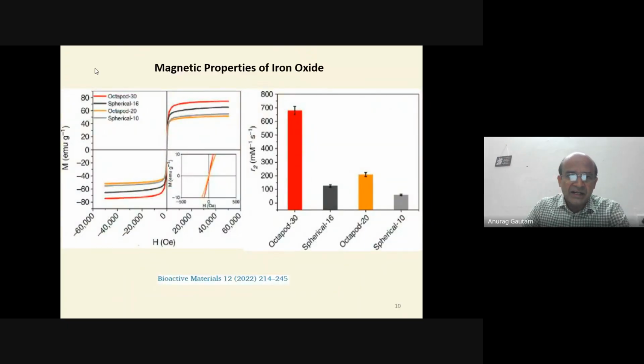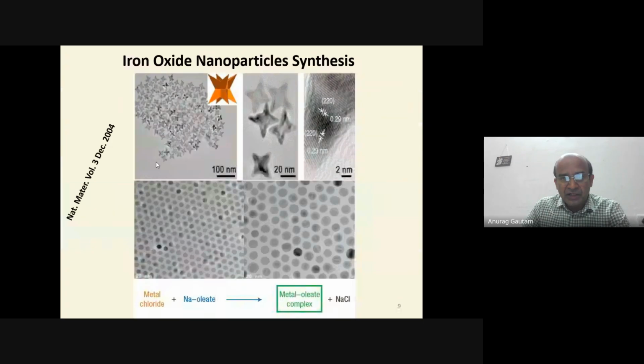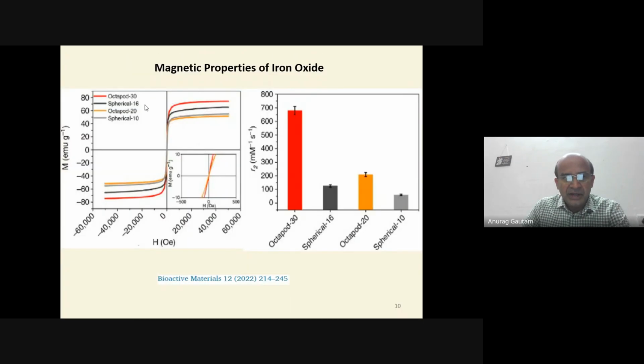And the basic thing, what I said, is that magnetization is very important, because when we are saying higher magnetic moment, the higher the magnetization, we can generate more T2 contrast. Overall, T2 contrast is very important to generate lots of contrast. T2 contrast, I'm saying, not the R1. T1 depends more on the surface phenomena. So how fast something comes to the surface of the particle, transfers the energy, and gets relaxed, and that energy is measured as a signal. So for T1 purposes, the magnetization is not important. The number of free electrons is important, but for T2 we use the overall magnetization.